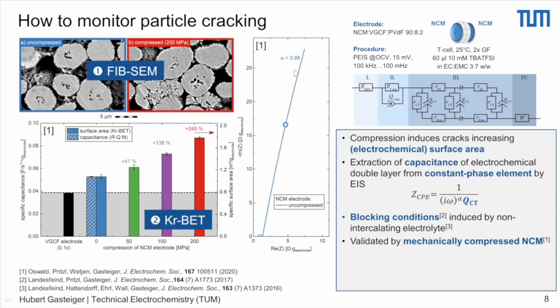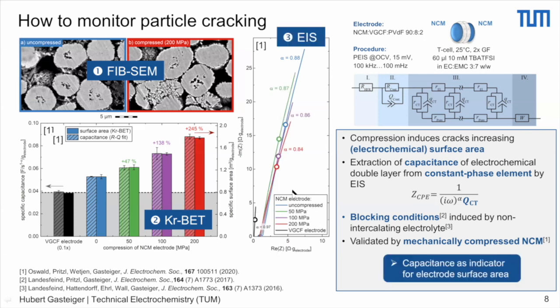So the constant phase element exponent is 0.88 instead of 1.0, which it would be for a capacitor. And then you see here a little bit of a contact resistance. So when we do this for all of these electrodes, we can acquire the impedance data, and we can analyze the capacitance from the impedance data. And then what we get here is exactly the dash bars here.